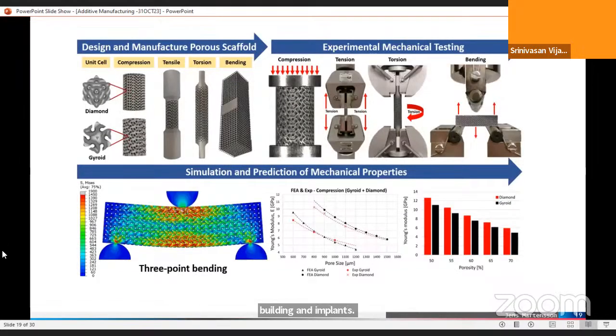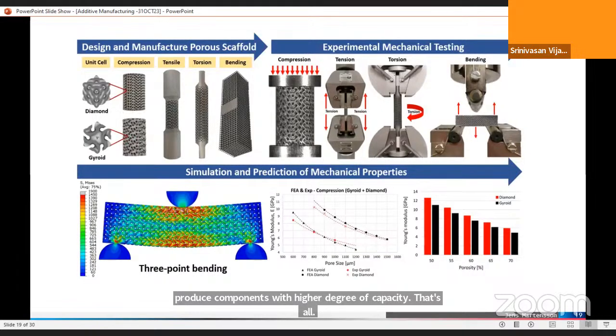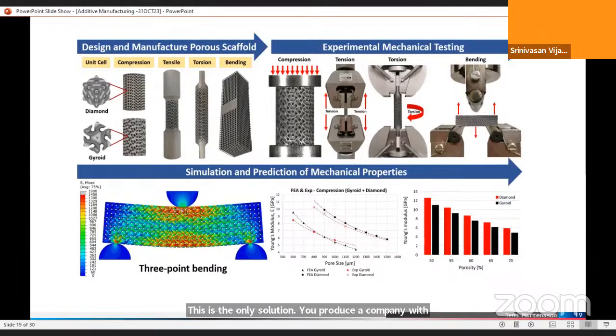And the best solution for reducing the stress shielding effect is to produce components with a higher degree of porosity. That's all. This is the only solution. You produce a component with pores. If you have many pores, the density will be reduced. Inside the pores, the bone will grow and clump together. The stress taken by the implant will be shared with the bone effectively.